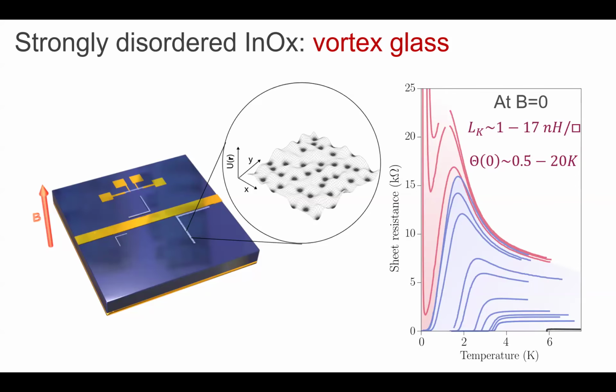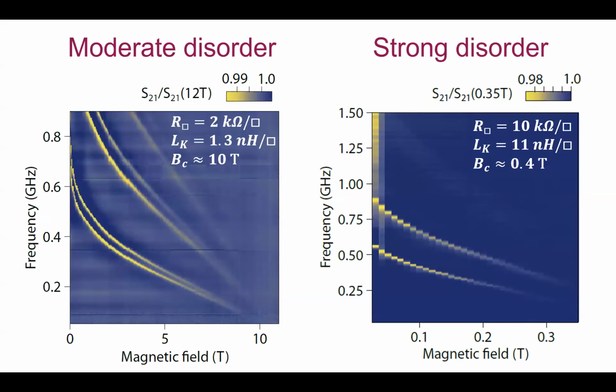Okay, so let's go to the vortex glass and this very disordered material. Now the inductance goes up to 10 nanohenry per square. The superfluid density is extremely small, below a Kelvin. And here is what we get. So I show you the raw data. This is the same plot as before. You can barely see the difference, but still you see that there is a decay of the frequency,